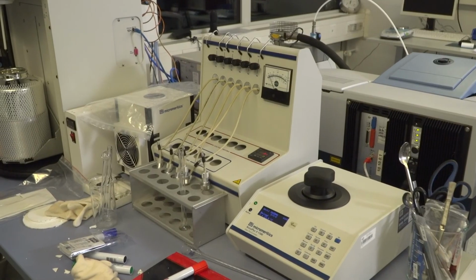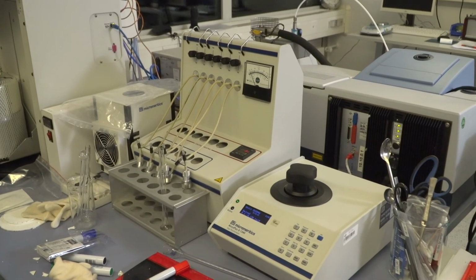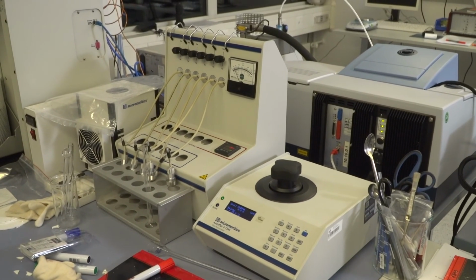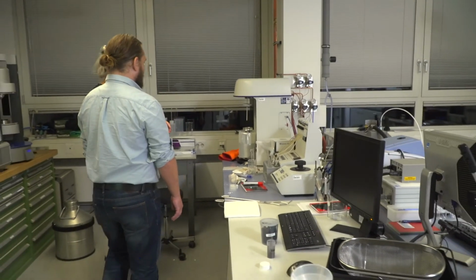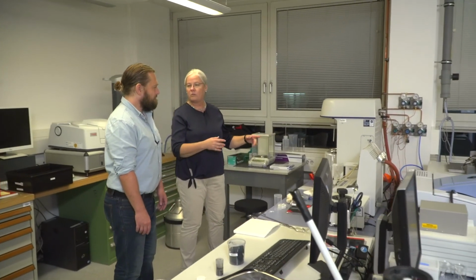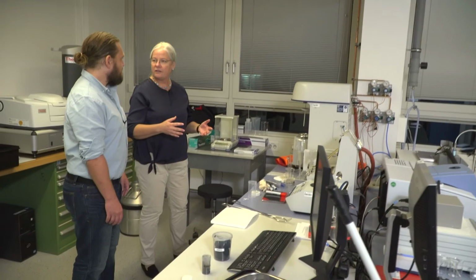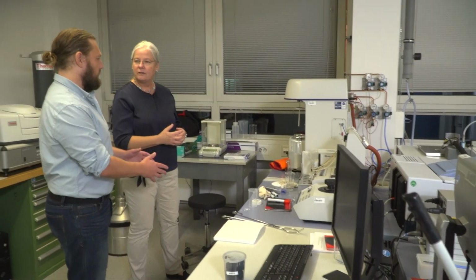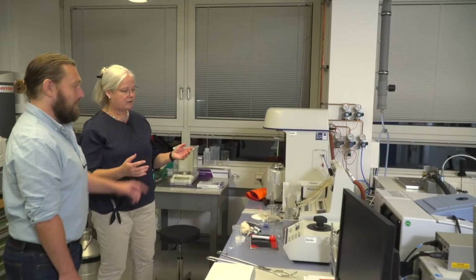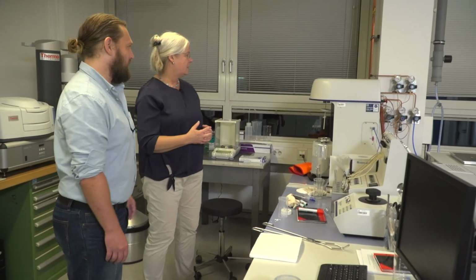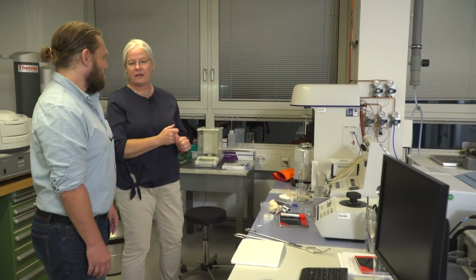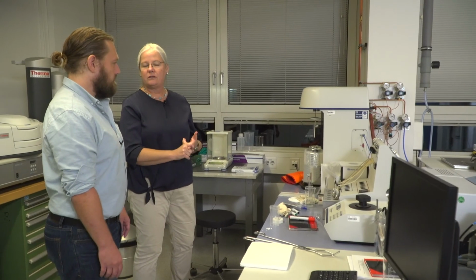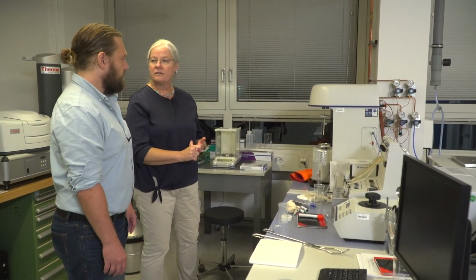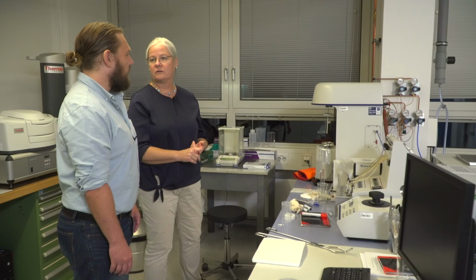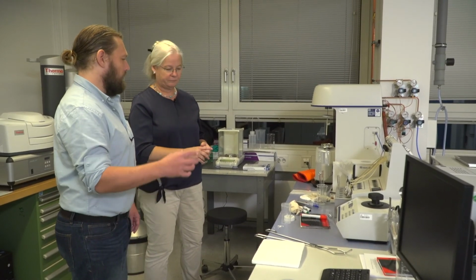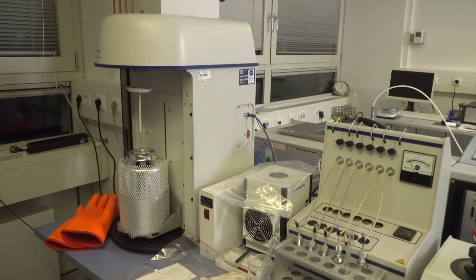And then I think we have a few more things here. These are more familiar aerogel analysis equipment systems. This is for normal BET and BJH measurements, to measure the surface area and the size of the pores. I believe this is a TriStar by Micromeritics, correct? Yes, it is working with nitrogen as the adsorbate, and we can also use CO2. With CO2, we measure the small pores, below 2 nanometers.